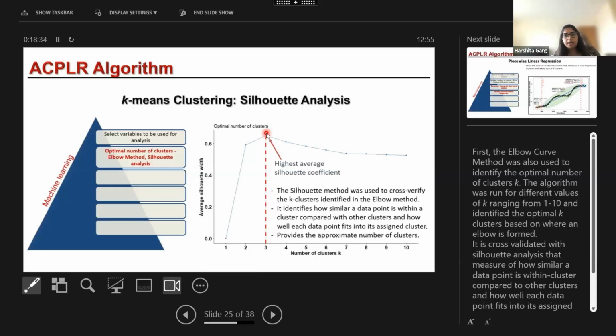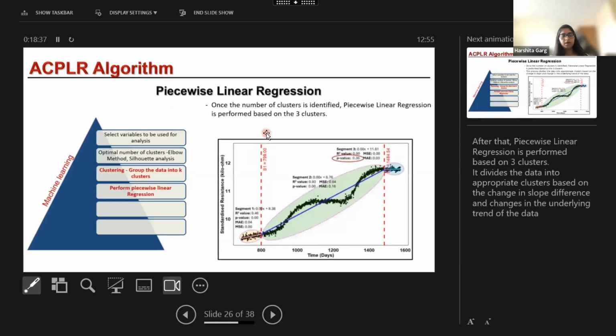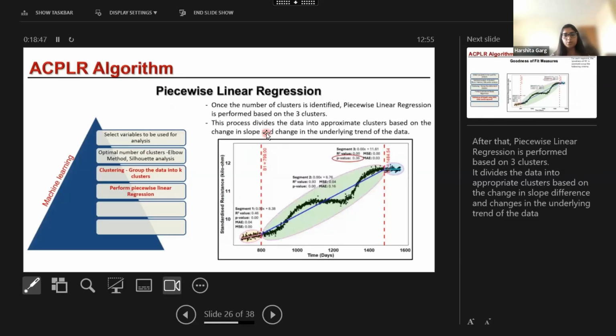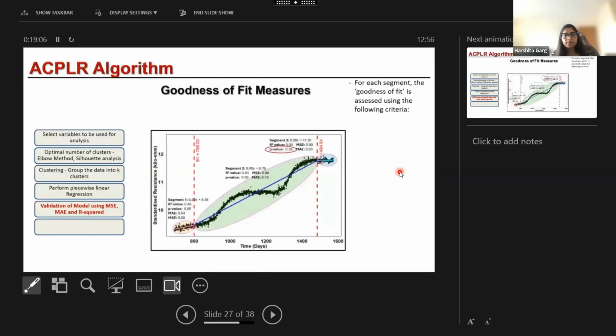So now the next step is to run the algorithm with the clustering and piecewise linear regression. It identifies 3 different clusters at 3 locations, dividing the data into those clusters based on a change in the slope and change in the underlying trend of the data. Here we can see that it provided 3 clusters, but they don't seem to be correct by looking at the data. So there is a need to put in a statistical method and set some criteria, so that if the results pass those criteria, the clusters are okay.